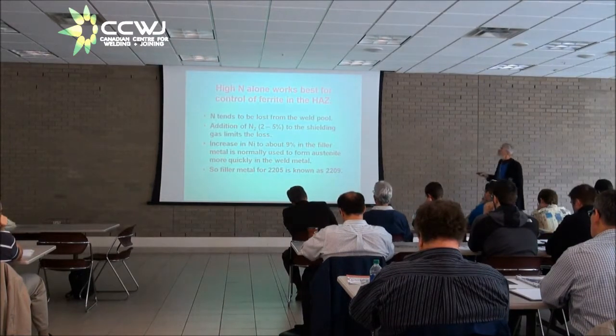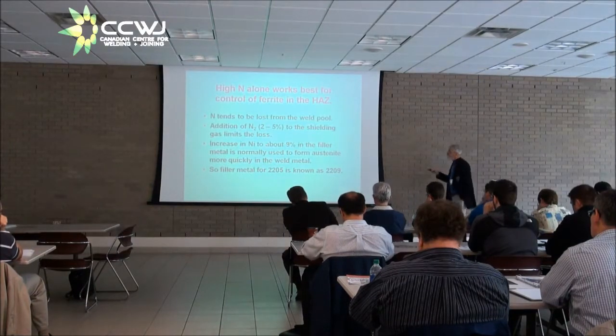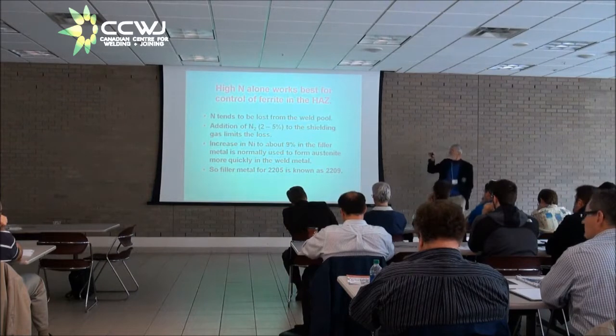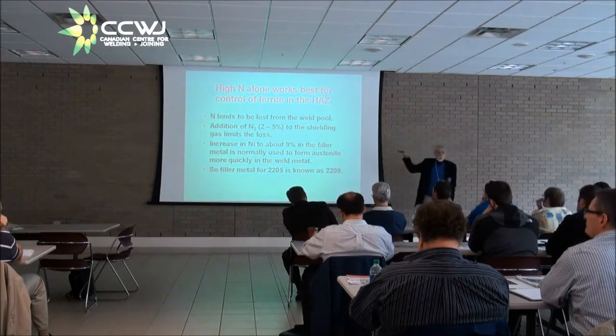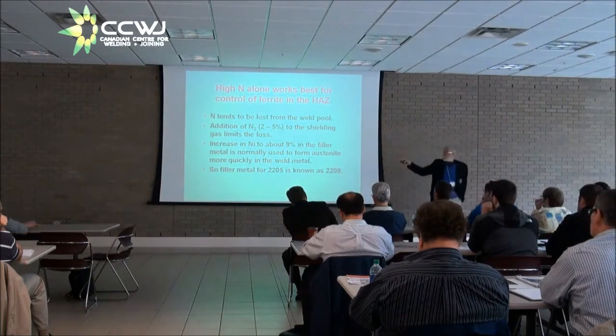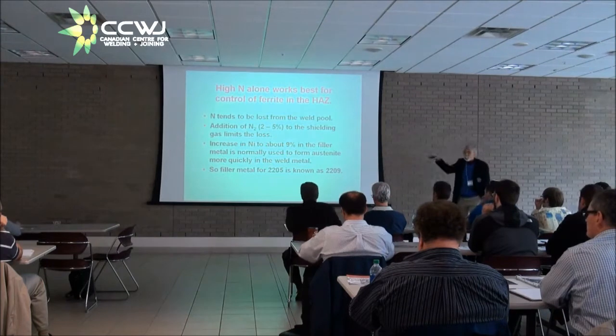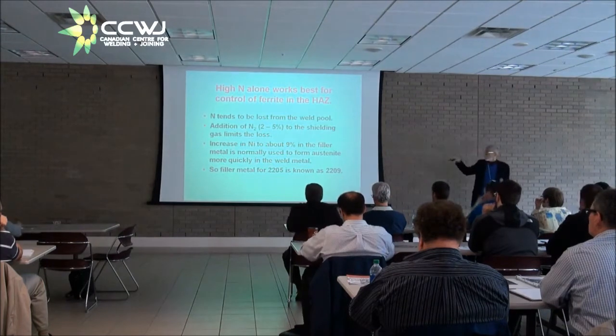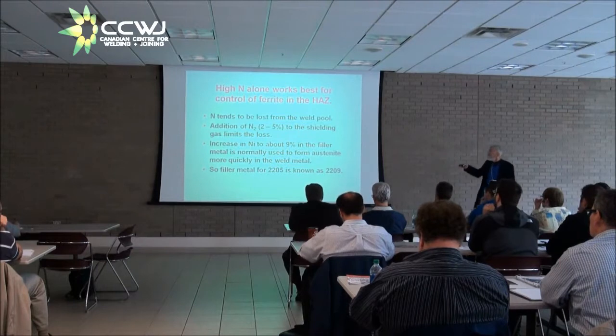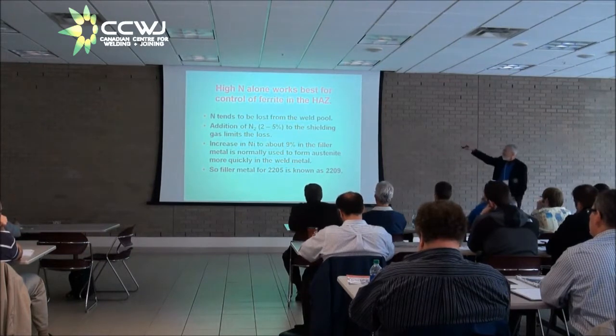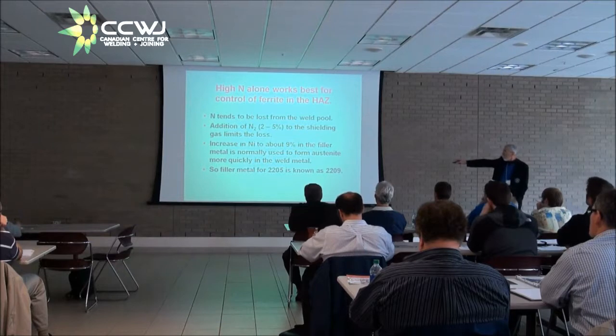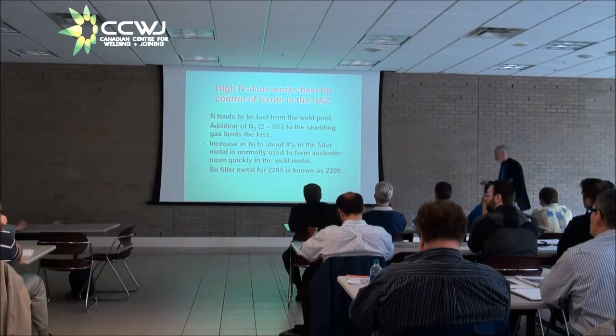So, one of the things we like to do now, as a result of this, is try adding nitrogen to the shielding gas to keep it in the weld metal. We increase the nickel content in the filler metal to 9% to help the weld metal. And with this addition of nickel, we now call the filler metal 2209 instead of 2205 to tell you that it's 9% nickel instead of 5% nickel.